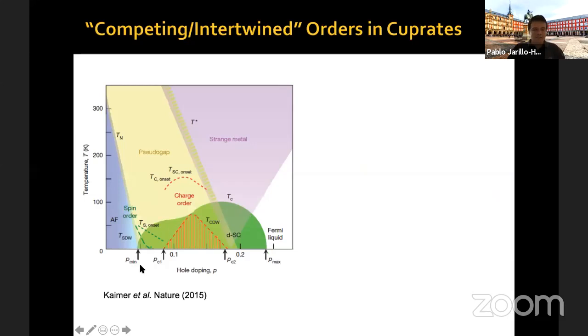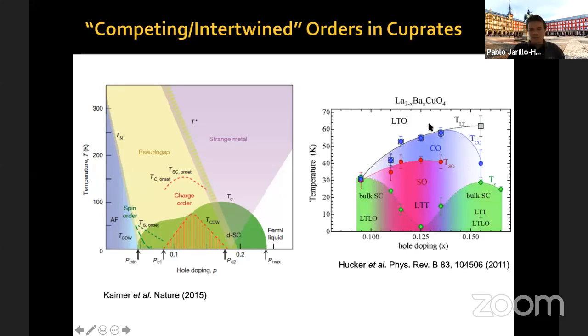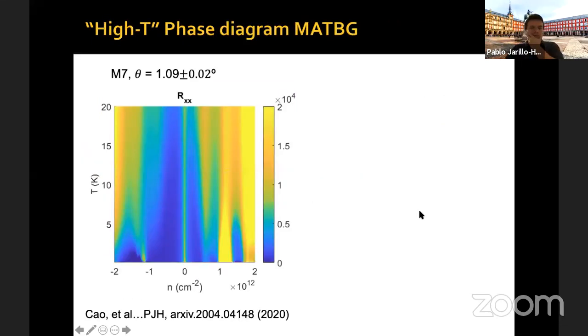Now, as you can see here in this phase diagram, the superconducting dome is not a single dome. It's made of these two domes with a depletion in Tc in between. Now, for some cuprates, such as lanthanum barium copper oxide, this depletion can be very strong, almost to zero, at this so-called 1/8, 12.5% doping, the 1/8 anomaly. This has to do with the presence of a competing order. In this case, it's a stripe order at this doping. So now let me show you a little bit about our samples.